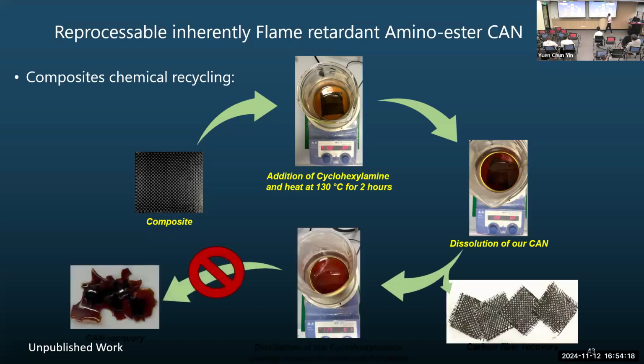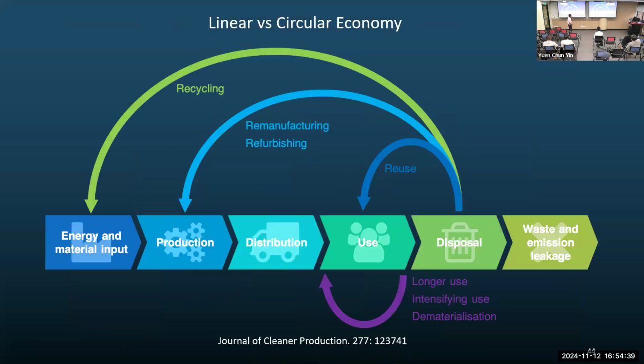But at this moment, we are not able to fully recycle the polymer yet, but we can recover the fiber very much. So this is unpublished work, but you can see that the aim is to be able to close the loop fully, I would say, with this kind of chemistry. So it's not alcoholysis, this is aminolysis, and this network is an amino ester network. So you can go back and forth, I would say.